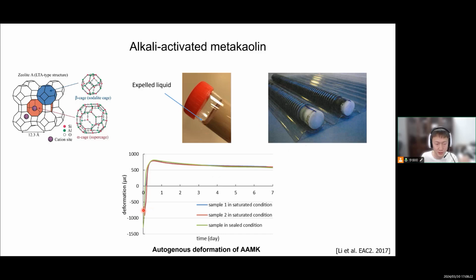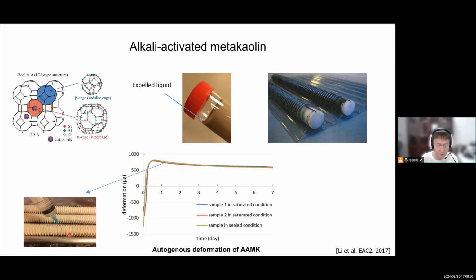And we can see the autogenous shrinkage curve, actually not autogenous shrinkage anymore, but shrinkage first, then expansion, then shrinkage again. So in the late and long period after the first stage, there will always be shrinkage. So we are curious whether the shrinkage is because of the same mechanism as for Portland cement, for example, self-desiccation. Is that the mechanism? So we used a saturated condition. We didn't fill the tubes completely, but just filled 2/3 of the tube to leave some space on top. And then I used a syringe to dig a hole, and then injected some solution, for example, alkali activator, on top of the surface.